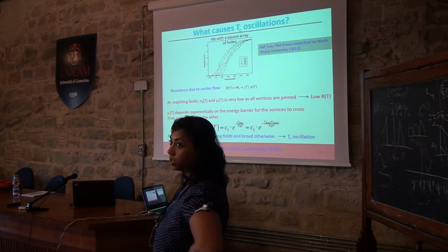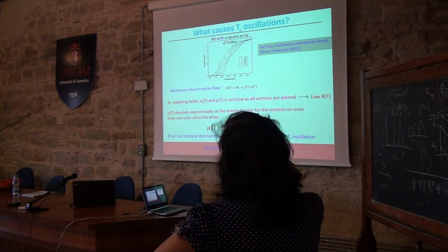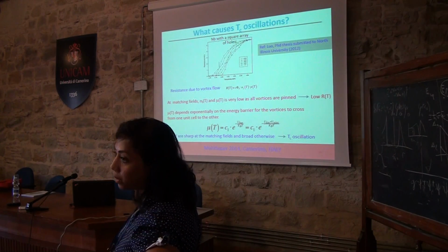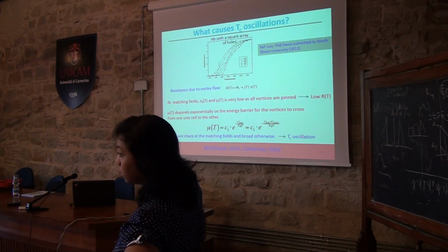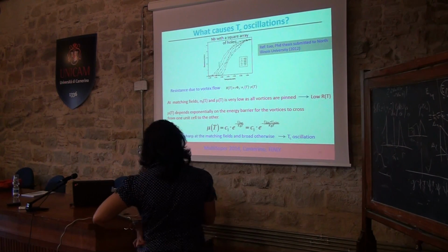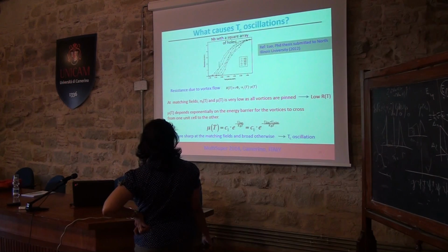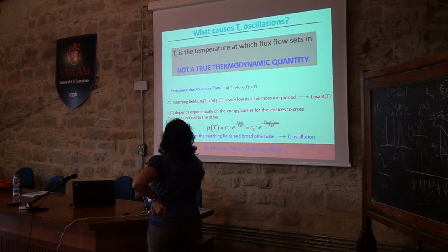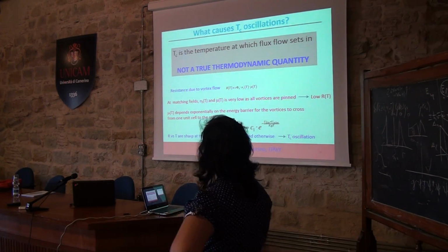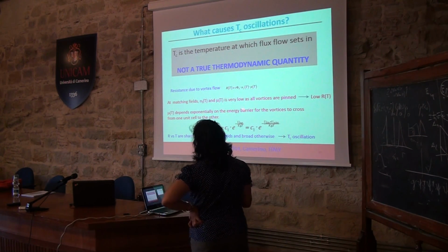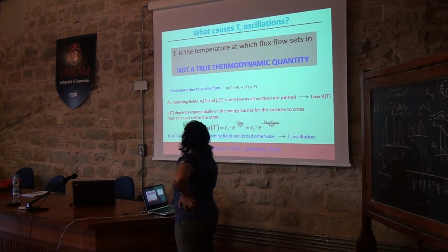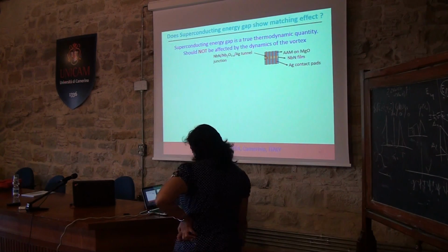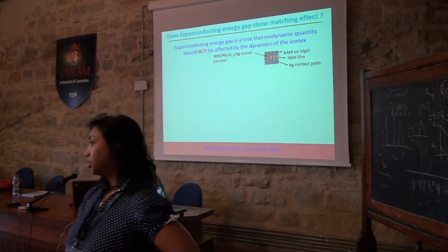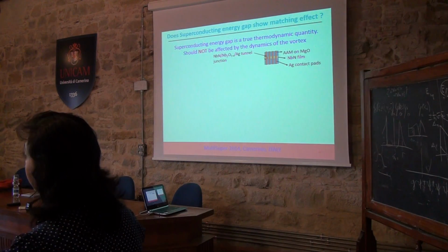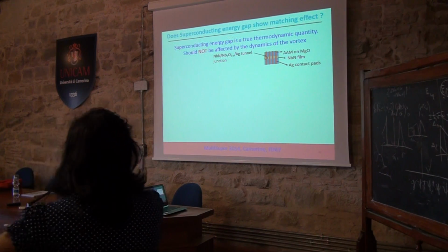So then what causes these Tc oscillations? What we feel is that this Tc we are measuring is not the real thermodynamic Tc. It is just the temperature at which the flux motion sets into play, the temperature at which the flux flow sets in. So this can be explained by a model which is valid in our case. Next, we measured the superconducting energy gap, and we tried to see whether we also see matching effects in this quantity.